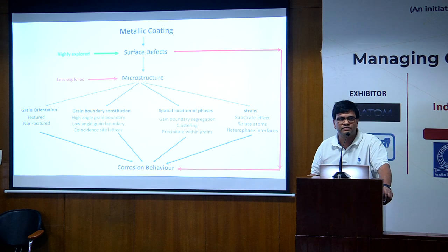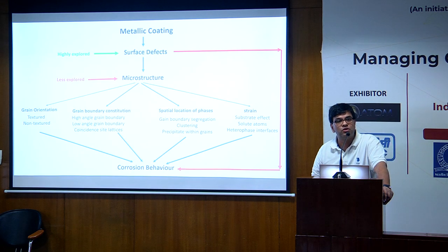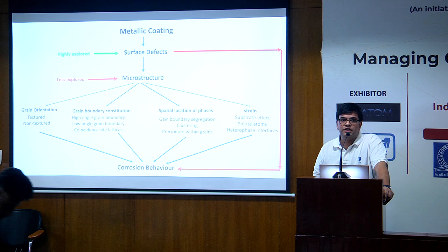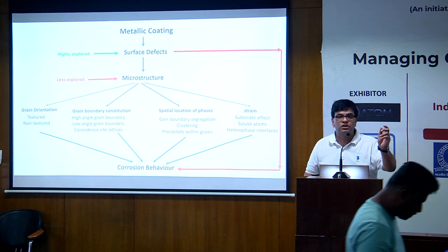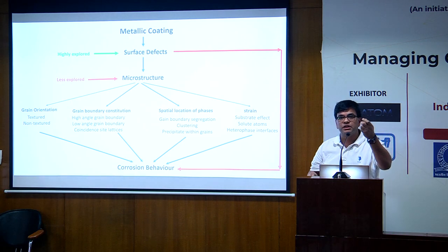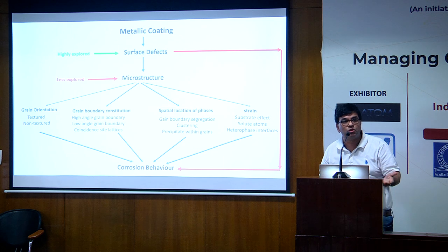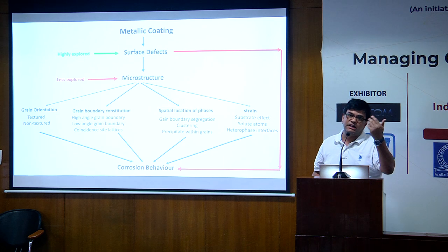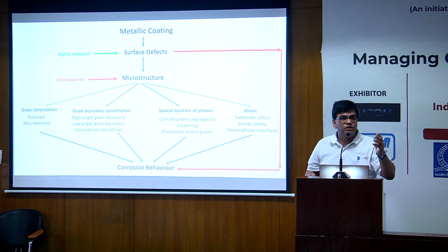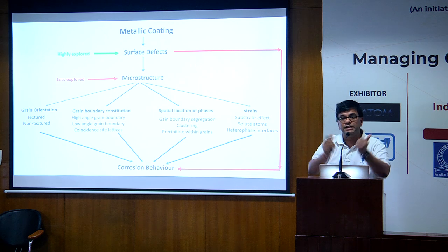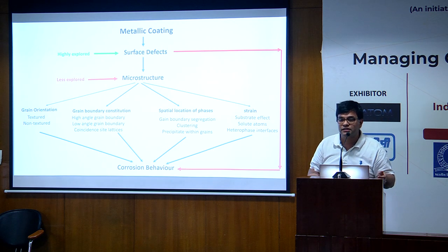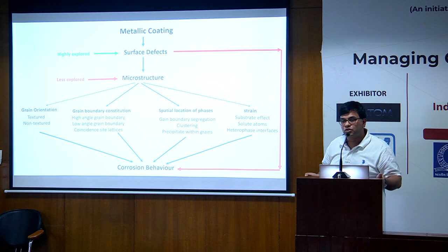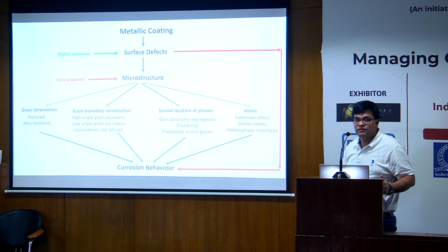There are several kinds of grain boundary: high angle grain boundary, low angle grain boundary, CSL boundaries and so on. People who are metallurgists, or who have done metallography in their undergraduate, know you do etching. You take a metallography sample and etch it to see the microstructure. What you actually do is corrode the grain boundaries, which dissolve and form a cavity that reflects the light in a different direction, and you see a contrast. So if you're looking at corrosion, the grain boundary constitution is very important.